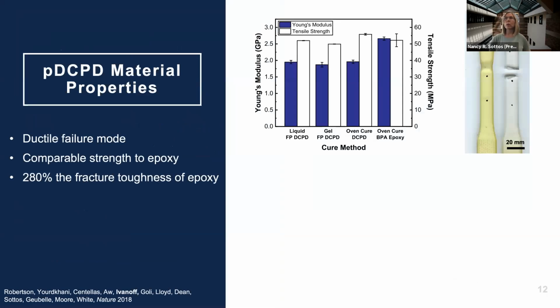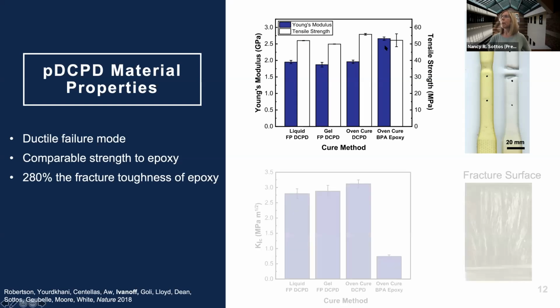And here I just show a comparison of those properties to a typical aerospace grade BPA epoxy. And when we started out, we were very careful to compare our frontally polymerized materials to if we just cured them in a traditional oven versus our traditional oven or autoclave cure of the BPA epoxy, and looked at the modulus. The modulus of DCPD is about 2.0 compared to 2.5 of an epoxy system, and the tensile strength or yield point is rather comparable.